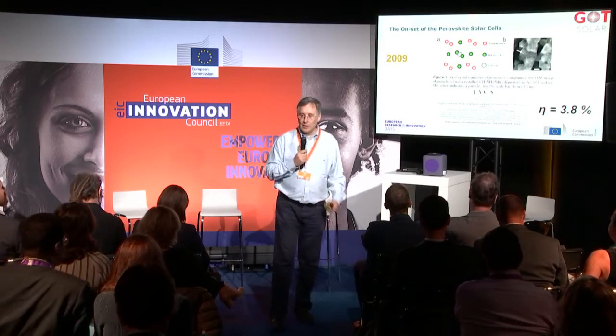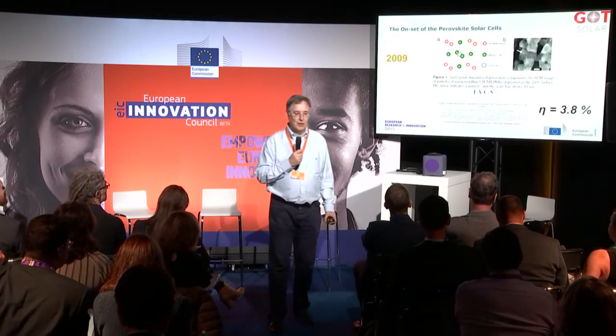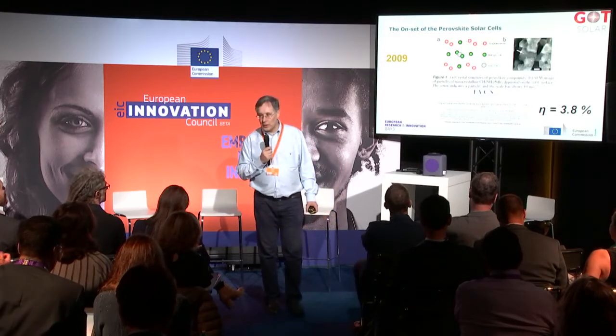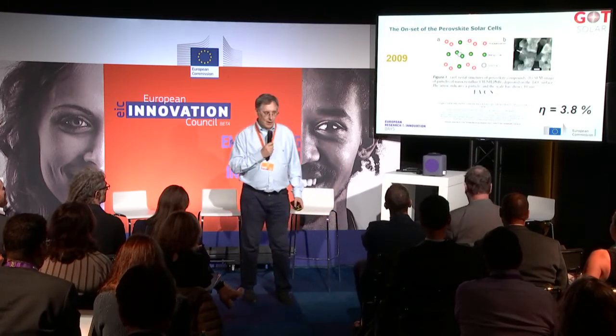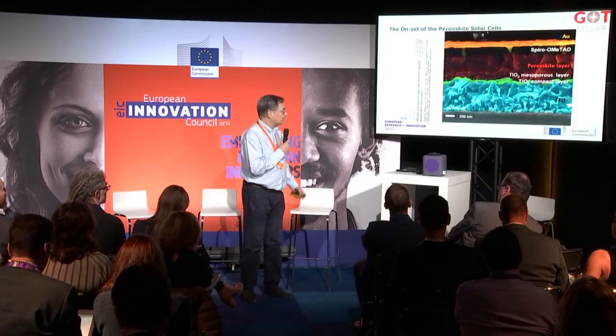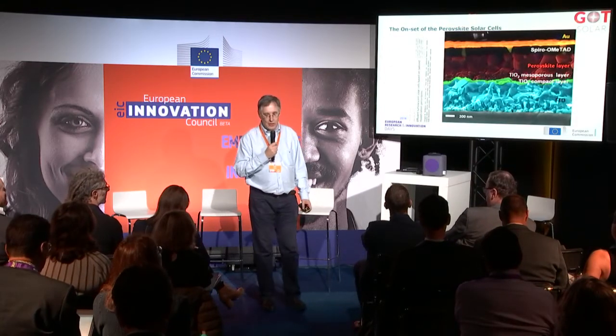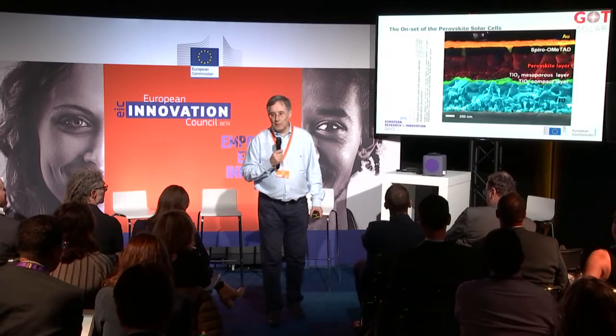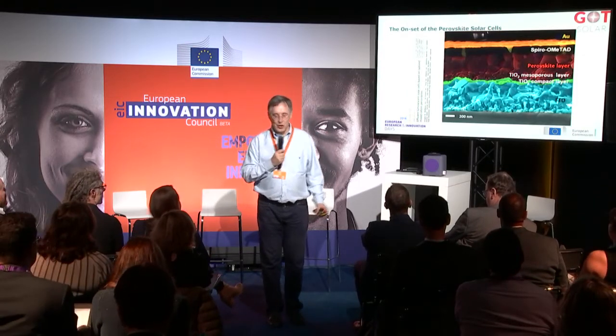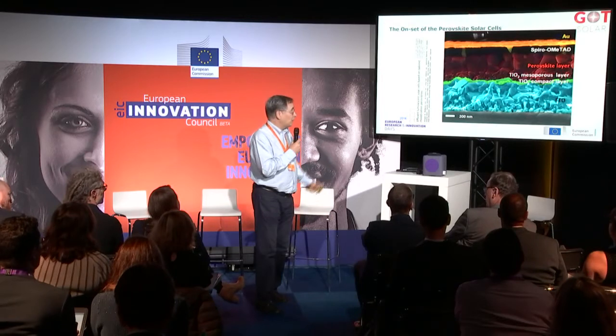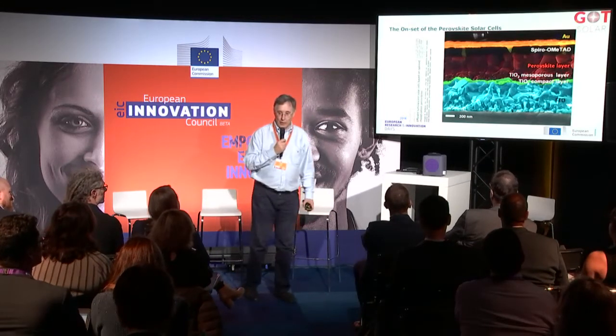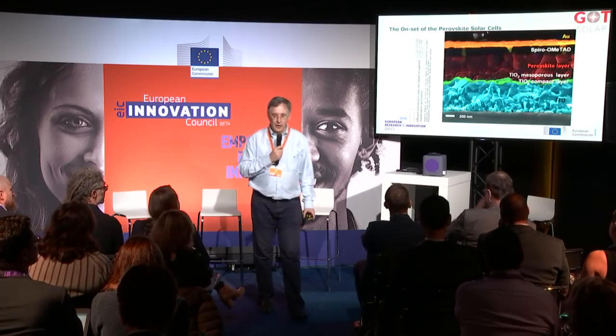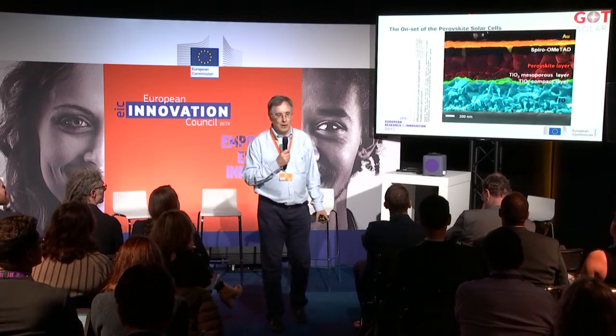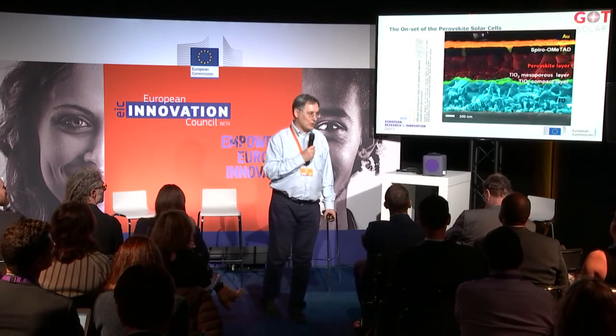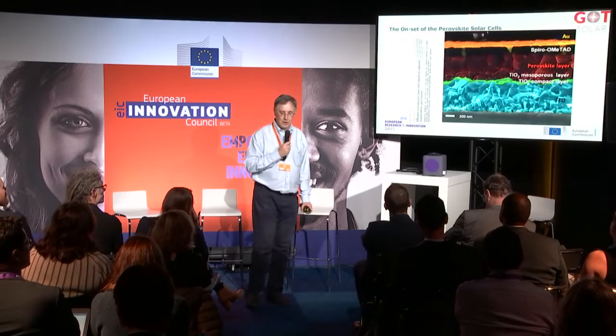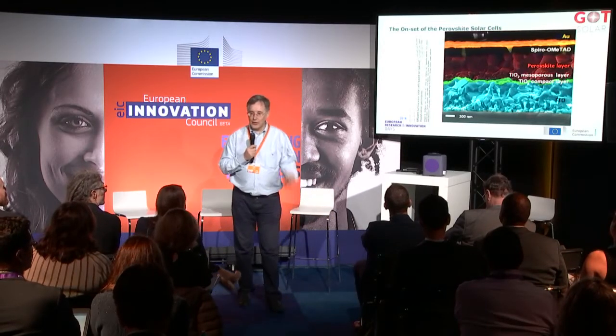I should remember that for small devices, silicon performs at 26% power conversion efficiency. This new technology is different from silicon because the absorber layer is just 350 nanometers. You can see it in red. 350 nanometers compares with silicon that is around 200 microns, so almost 1,000 times thicker. This is a very thin layer.